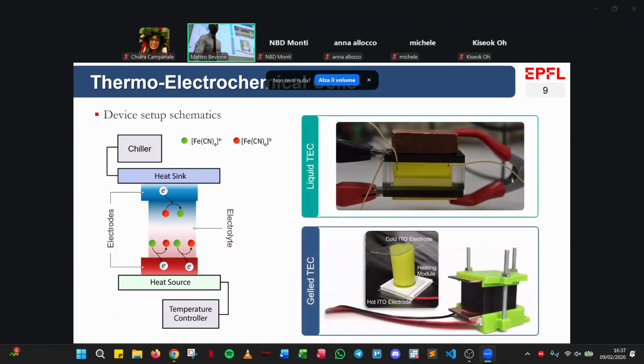So in particular, this has fundamentally the same configuration as a thermoelectric device. We always have a hot side and a cold side, and we have a liquid in between. In the liquid are dispersed some redox couples, which undergo the electrochemical reaction. And in particular, this electrolyte can be either liquid, as I mentioned, water-based for example, or gel. And the gelled ones are particularly interesting for a reason we will see afterwards. But first, let me just introduce to you how this device works.